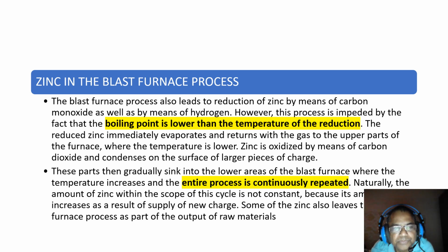Today we are going to talk about the role of zinc in the blast furnace process. The very important thing that we have to learn about zinc is that reduction of zinc oxide is at a much higher temperature than the boiling point of zinc. Hence, as soon as zinc oxide gets reduced, it vaporizes and takes shelter in the stack of